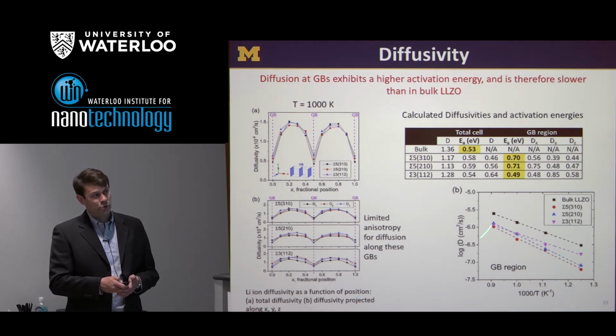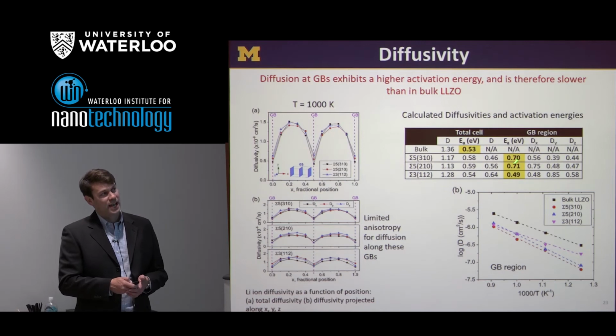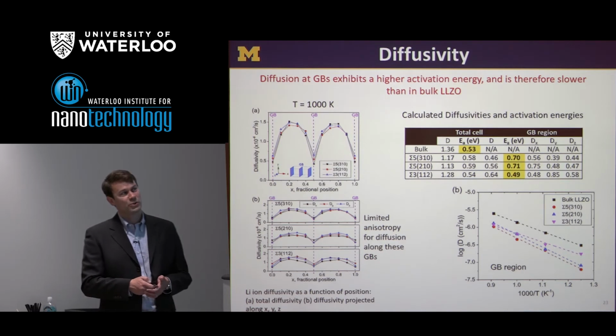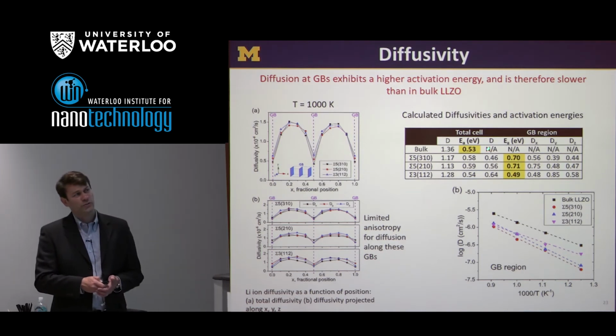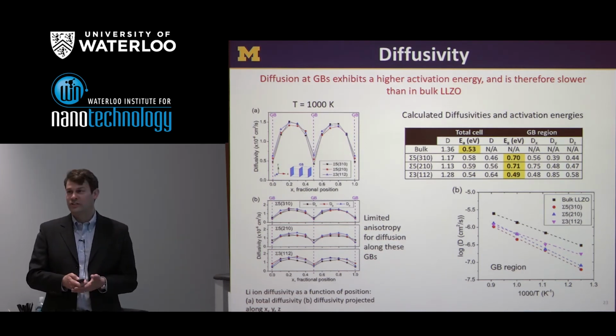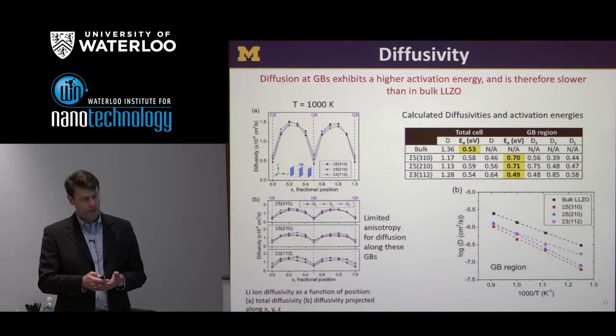We can also make Arrhenius plots to estimate the activation energy for diffusion. And so what we found, and highlighted here in yellow, these are the activation energies in the grain boundary region for those 3 grain boundaries, and this is the comparable value in bulk. And so you can see for 2 of the 3, we've got an increased activation energy, again, consistent with slower diffusion. One of the activation energies is roughly comparable to bulk.